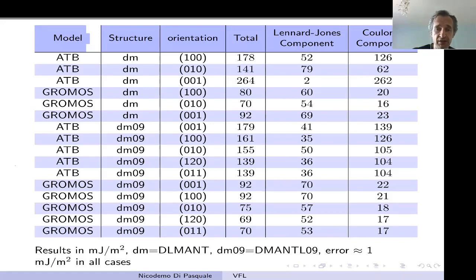And when we moved to united atom models, these interactions again became much smaller, especially for the DM09 structure. Again, it might be consistent with a polar component of surface free energy that is available from IGC experiments. So it looks like we are converging on the results, and we are hoping that molecular simulation can have predictive power in terms of characterizing surface free energy for different molecular crystals.